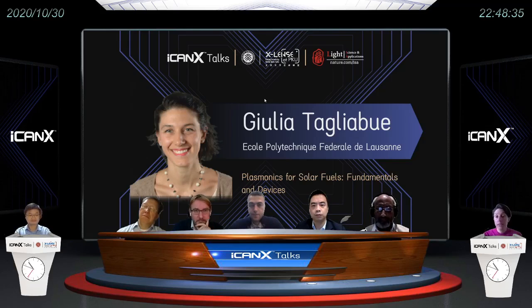It's really on the selectivity, because the problem is that, for example, copper can generate carbon monoxide and ethylene, but at the same time ethanol, which is liquid. And so now you would need a humongous amount of energy to separate these products. And this would completely wash out the advantage of being able to do CO2 reduction in the first place. So the challenge of selectivity is really what is preoccupying most of the community at this stage. Okay, thank you.